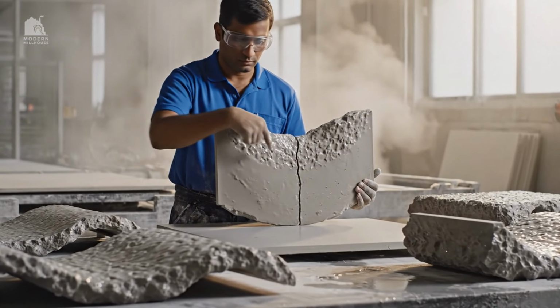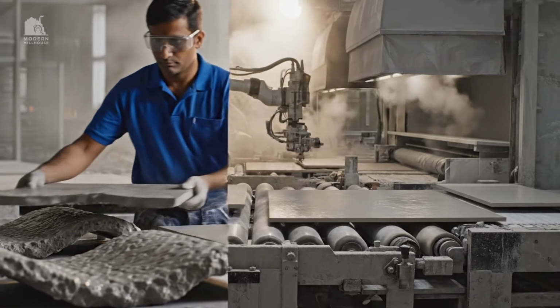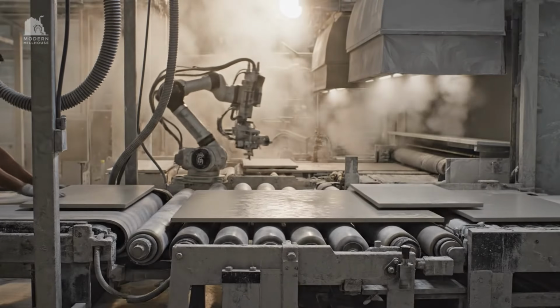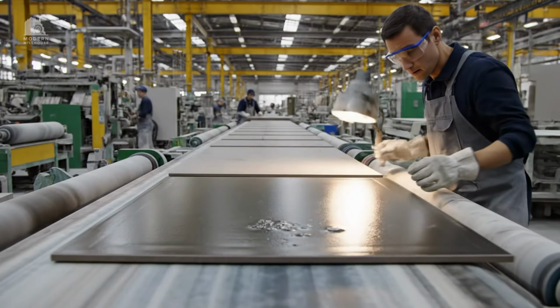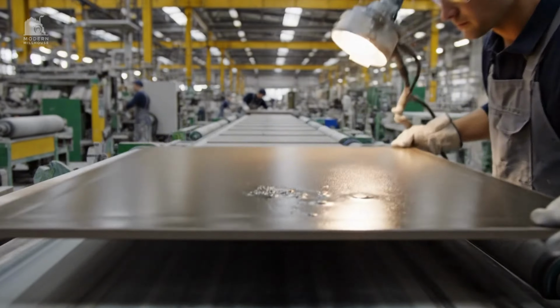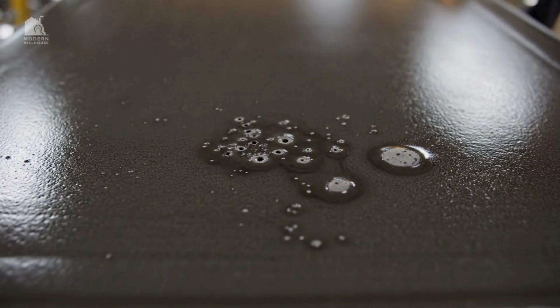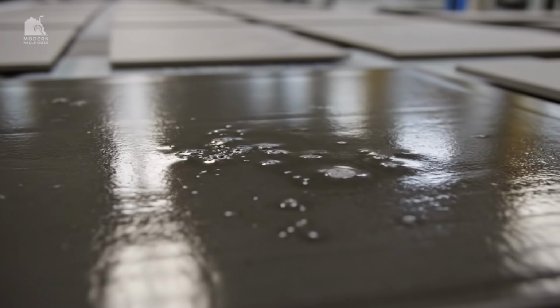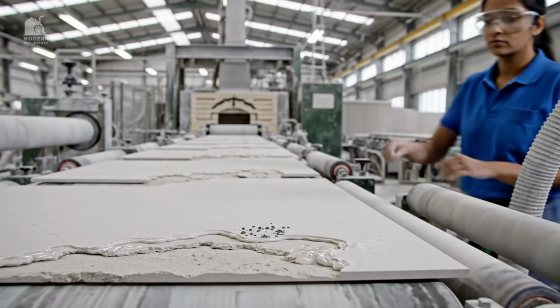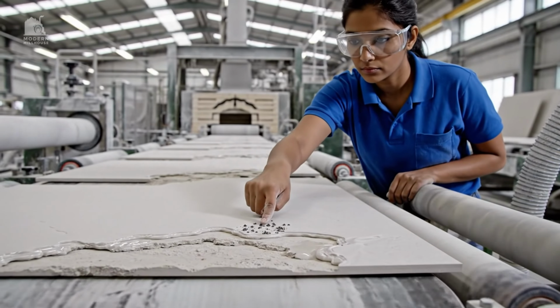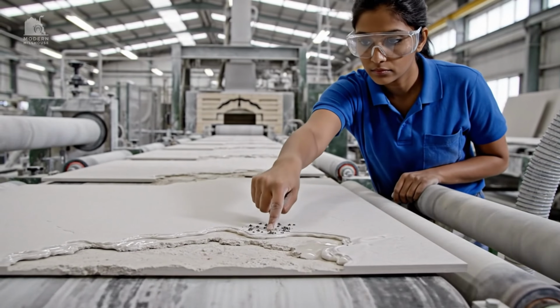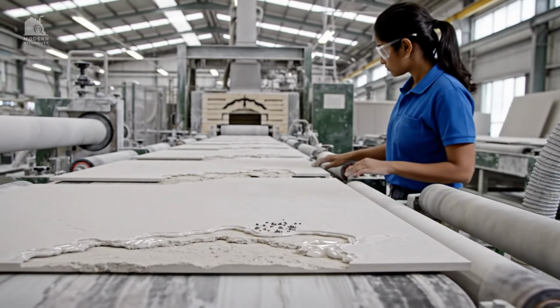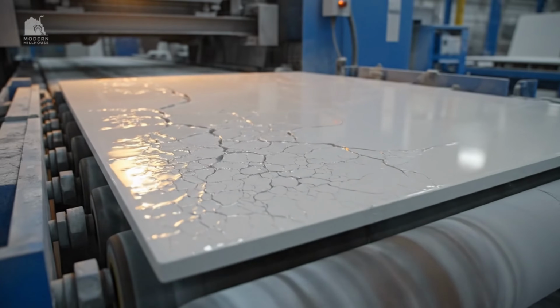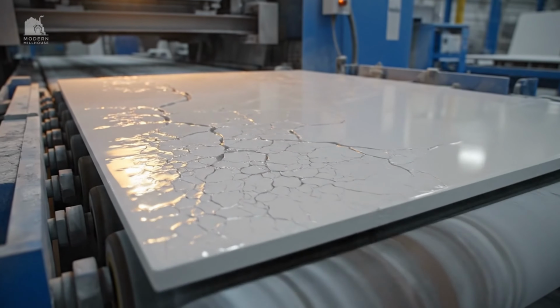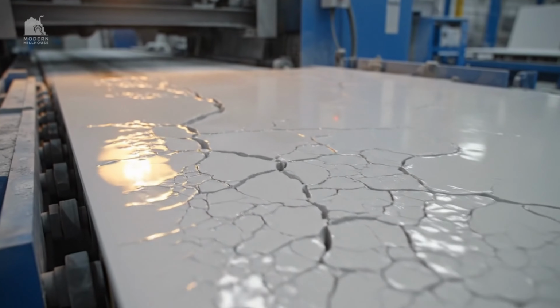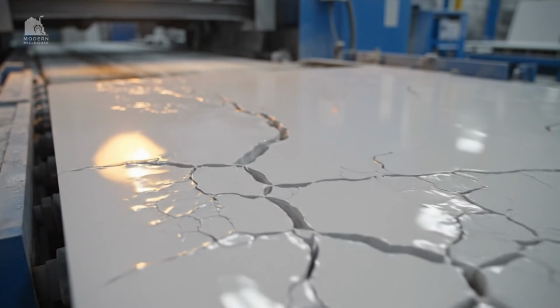A crack that starts at the edge often points to handling damage or uneven drying. A blister that appears only in dark areas can point to printing solvents or organics burning out too late. A wave in the surface can point to uneven glaze thickness or roller issues inside the kiln. This is why factories keep detailed process logs. Defects are diagnosed like engineering failures, not like cosmetic flaws.